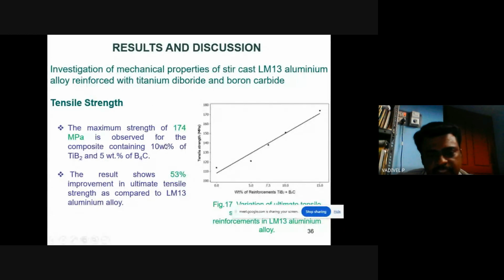So the maximum weight percentage of the ceramics gives the high tensile strength that we obtained, 174 megapascal. Compared to the earlier result, it is improved, with the ultimate tensile strength 53 percentage higher than the LM13 aluminum alloy. So this is a very good result which we obtained after n number of iterations.